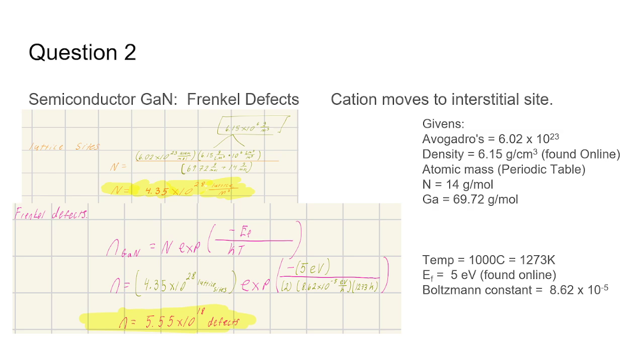And then we plug that into our main formula to find the number of Frenkel defects by doing number of lattice sites times exp of negative 5 eV divided by 2 times Boltzmann constant times temperature, and that gives us 5.55 times 10 to the 18 defects.